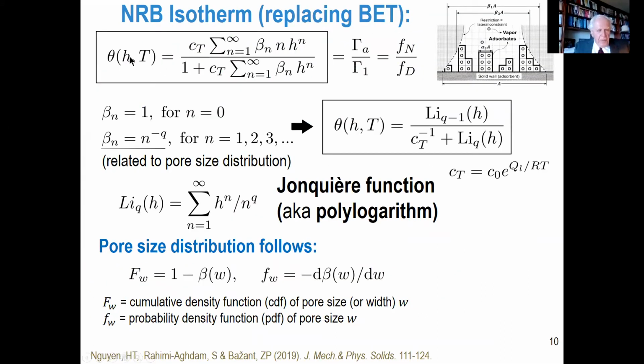So this leads to adsorption given by this theta, which is fraction of water content compared to saturation, which depends on humidity, also temperature, of course. And it is given by a ratio of 2 sums with a thermal coefficient, which is very important to change temperature, liquefaction heat here. And these sums, it so happens, can be explicitly obtained. They are well-known sums. They are called Jonquière function, which is readily available on Mathematica instantly, just like a sine function, and denoted as Li with the parameter.